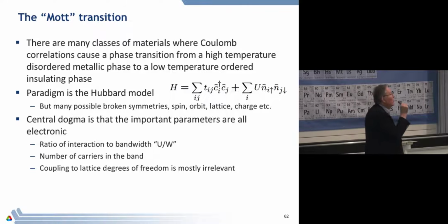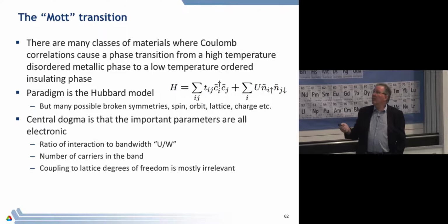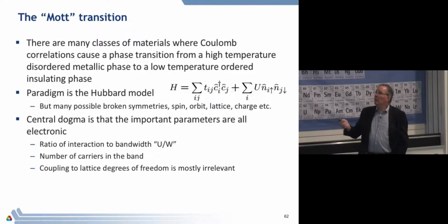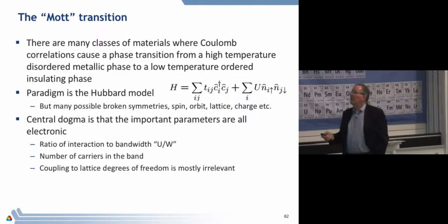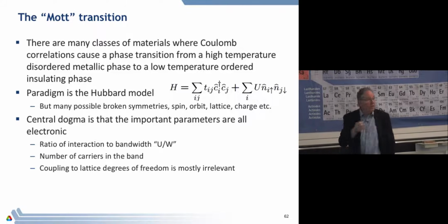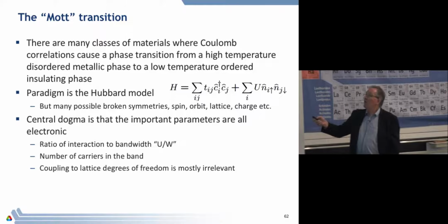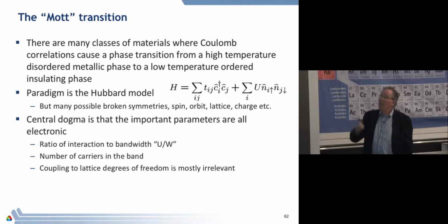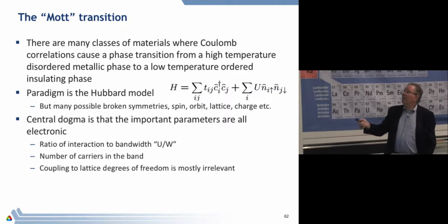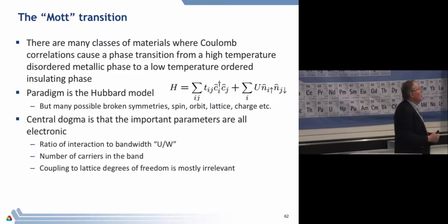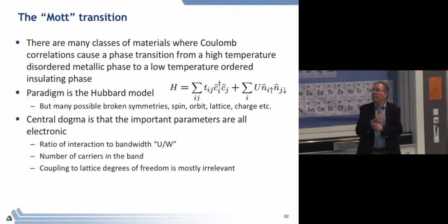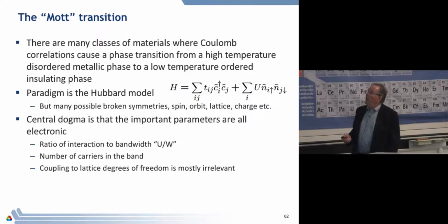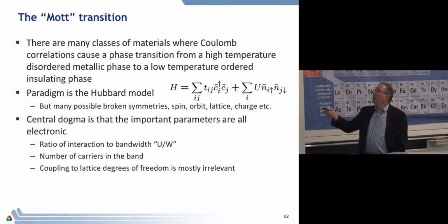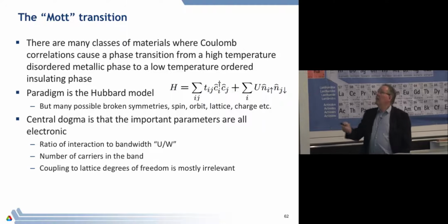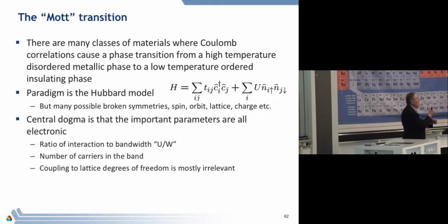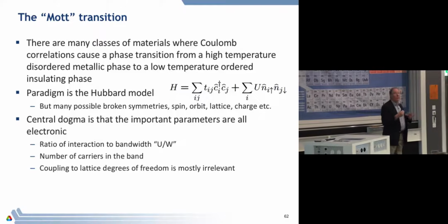Now, a paradigm for that, for physicists, is to think about a model which is broadly called the Hubbard model. And this is just the hopping of free electrons on a lattice given by some hopping parameter. So this is the electronic band structure, if you like. But then an energy penalty that you pay of just the Coulomb interaction of having two electrons on the same site. So what we know is in a model like this, if U is big enough in comparison to the bandwidth, this term will dominate. It will prevent two electrons being on the same site, and I will localize into some kind of insulating phase.